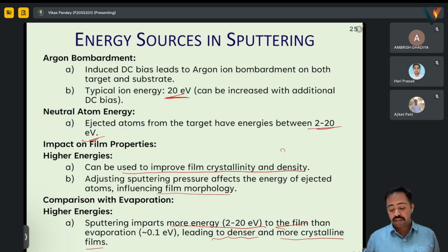And that is why sputtering techniques are even used to create nanostructures. You will see sometimes people making nano flowers and nano rods using sputtering, optimizing the parameters, like at specific energy as well as specific gas pressure. They are able to make different nanostructures, and this is due to the crystallinity, which is due to the energy carried with these materials. Then this can even be used for alloys and reactive sputtering. Here, the ratio control is very good.